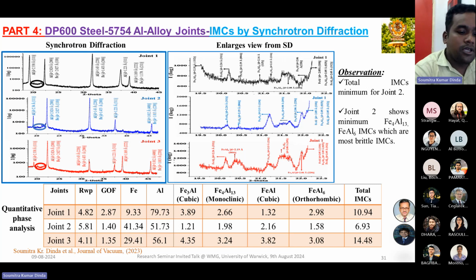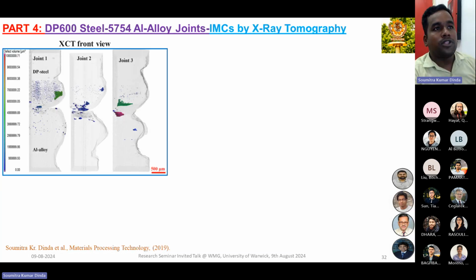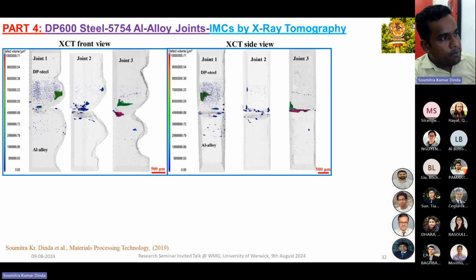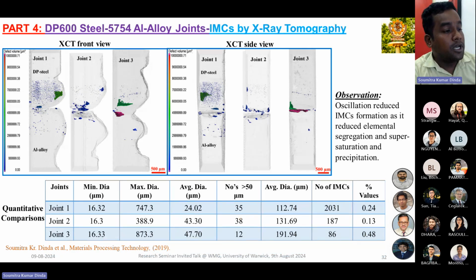So here we found both porosity and intermetallic defects in our DP600 to 5754 aluminum alloy joint. Then we went for the visualization of intermetallics, just like we did for porosity. With the same sample, we did a tomography study for the porosity defects and for the intermetallic defects.